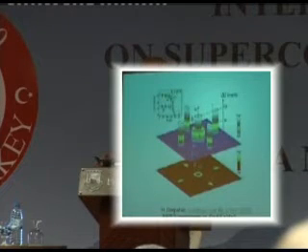Conclusions. Type 1 superconductors so far have found this. So the combination of vortex repulsion and attraction in the same material leads to the appearance of novel vortex patterns, exotic vortex arrays, vortex clusters, vortex stripes. These patterns we have directly visualized by using decoration and scanning microscopy, and we did some analytical modeling, but also large-scale molecular dynamics calculations, and they are in good agreement with our experimental observations.